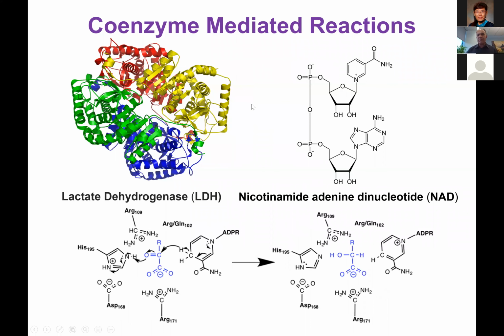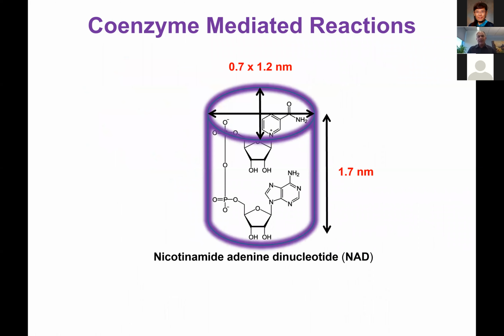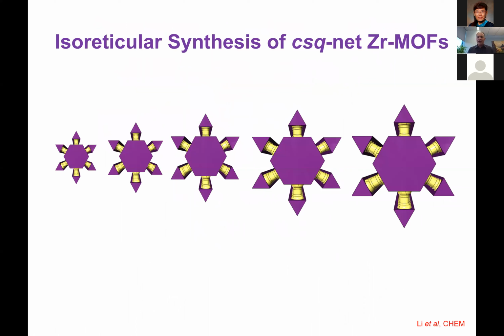And this large molecule here is the NADH, the coenzyme. And you could see this is really large, not a small nitrogen or a CO2 molecule. And this is a very well-studied mechanism that you need all 3 components for it to work the right way. This is just putting the size of that molecule in perspective. Obviously, the easiest way is just keep expanding those linkers and make a larger and larger MOF.